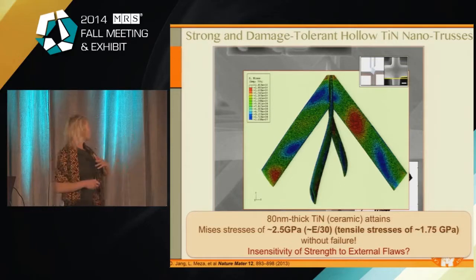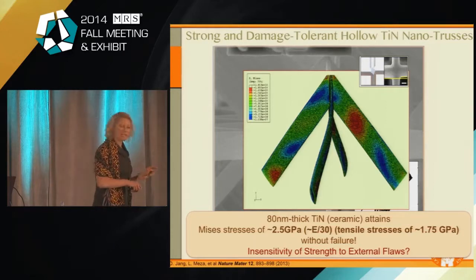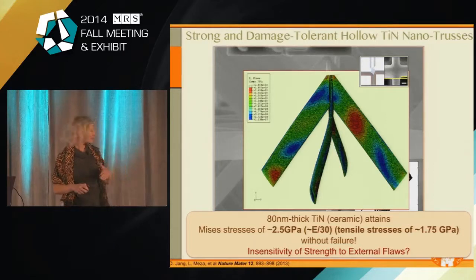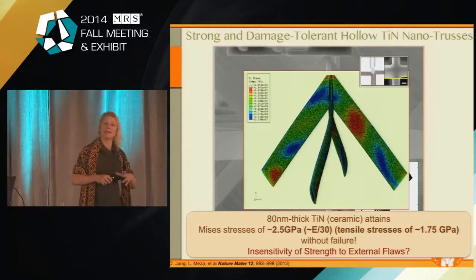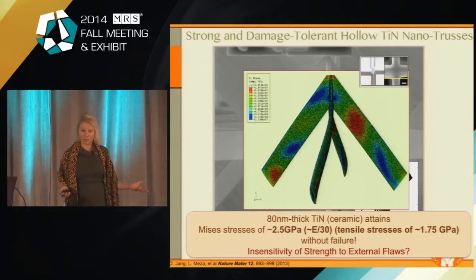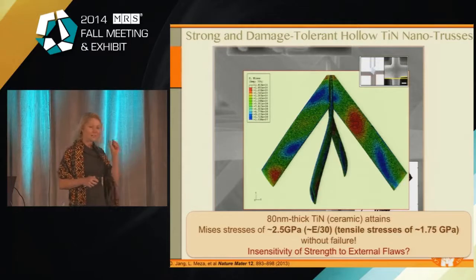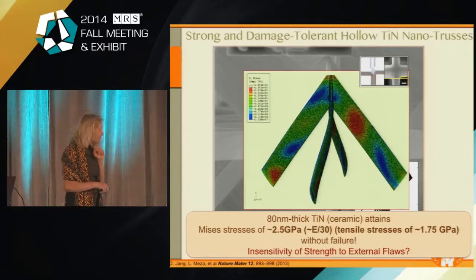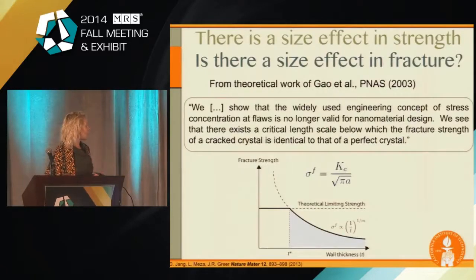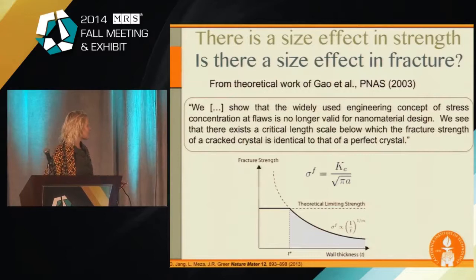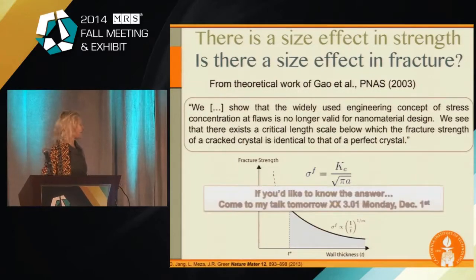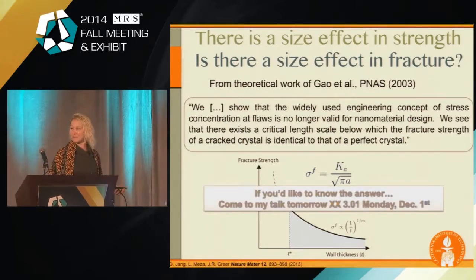All ceramics absolutely should have broken already by this point, but these don't for some reason. And they do this over multiple cycles. I believe they did it over 30 cycles and they never broke and there were never any cracks forming in there. So there's something very interesting going on in these nano-sized ceramics that are supposed to be brittle. So maybe there really is some kind of an insensitivity to flaws that's going on. That's the big question, especially since there is this theory here. And so I'm going to leave it on a cliffhanger because I think my time is about up.